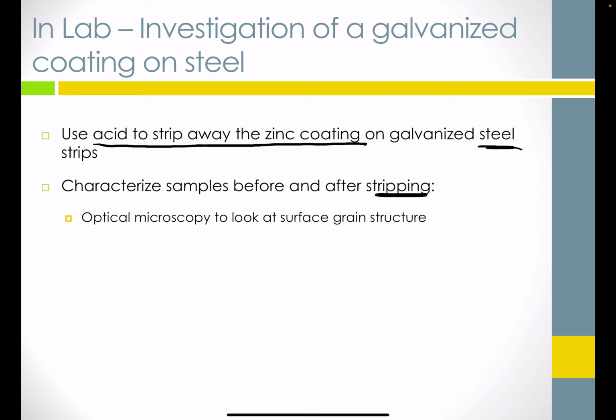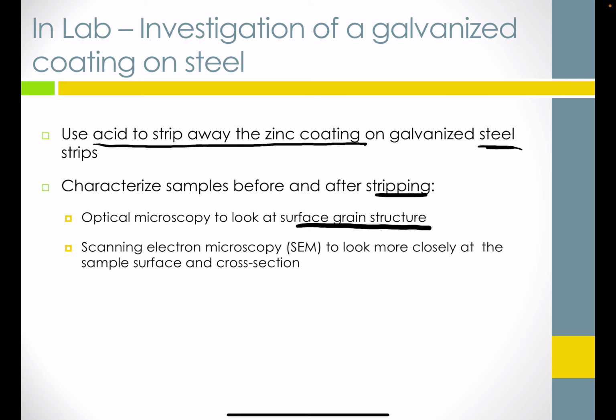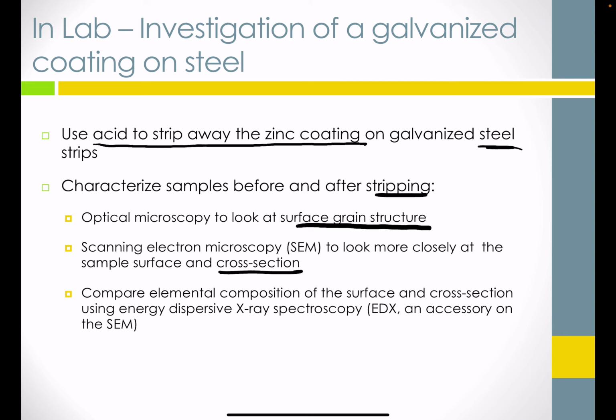We'll use microscopy to look at the surface grain structure. We saw it in a slide earlier in this video. We'll also use SEM to look closely at that surface before and after this acid stripping step, and look also at the cross section there as well. And then we'll compare the elemental compositions, that is the content of zinc, the content of iron at the surface and in the cross section, and use energy dispersive X-ray spectroscopy, EDX, here to help us do so. This should help us prove whether or not we've removed all the zinc and exposed more of the iron below.